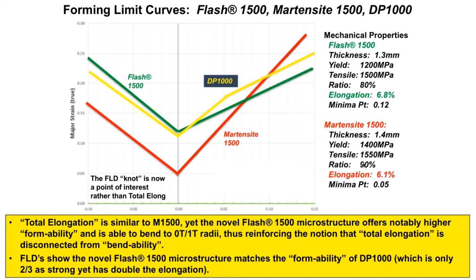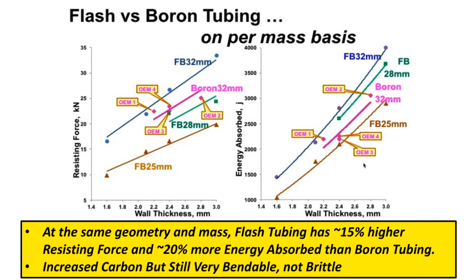We spoke about energy absorption a little bit before when I showed you that crush can. This is also some data that Hyundai Kia was kind enough to allow us to share. And in the chart on the left, we talk about resisting force on the vertical axis and wall thickness on the horizontal axis. We have some examples of some curves plotted because Hyundai Kia was kind enough to test tubing diameters from 25 to 32 millimeters, as signified by FB 25 millimeter up to FB 32 millimeter, but also in wall thicknesses from 1.6 to 3.0 millimeters.